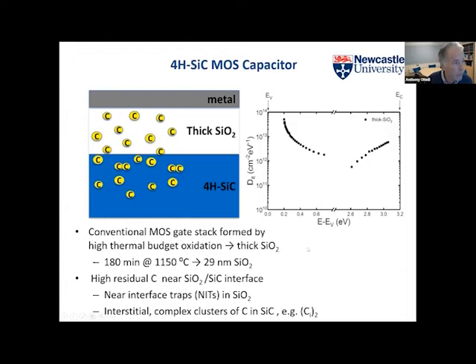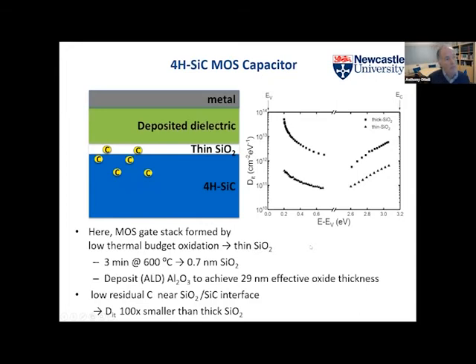So having worked on silicon for a lot of years, I reasoned that perhaps an alternative would be, well, you just don't grow quite as much oxide. If you think of, I think it was the 45 nanometer CMOS technology, what people did was move to a high K dielectric for different reasons. But even when they'd gone to high K dielectric, they had to go thin oxide just to make sure that the thing worked properly, to get the defects sorted out by this thin oxide.